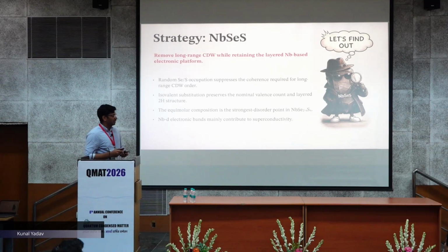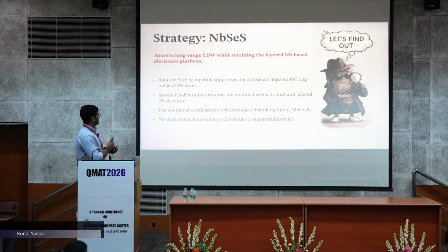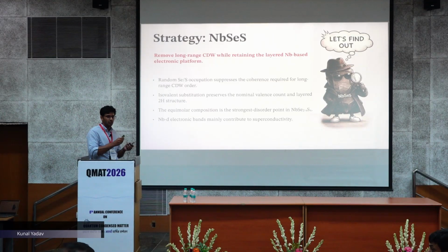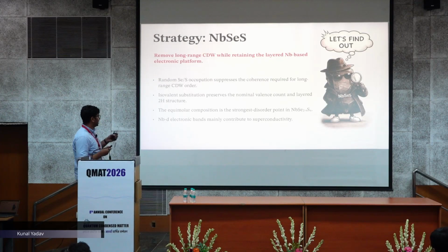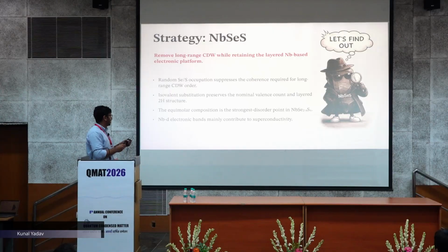So the strategy is clear: we have to remove the long range CDW ordering while retaining the layered Nb-Se layered electronic platform. So we randomly substitute selenium with sulfur, where random substitution suppresses the coherence required for long range CDW ordering. We are using sulfur, which is also isovalent to selenium, so we are protecting the valency and the layered 2H structure. Also, the equimolar composition NbSeS is the strongest disordered point where CDW can be suppressed in the best way. Also, a very important point is that the superconductivity here is mainly dominated by Nb d orbitals.